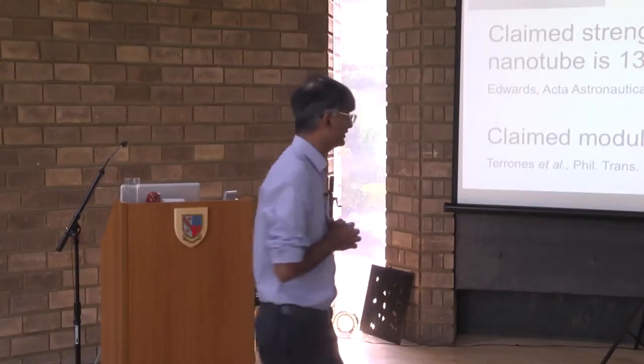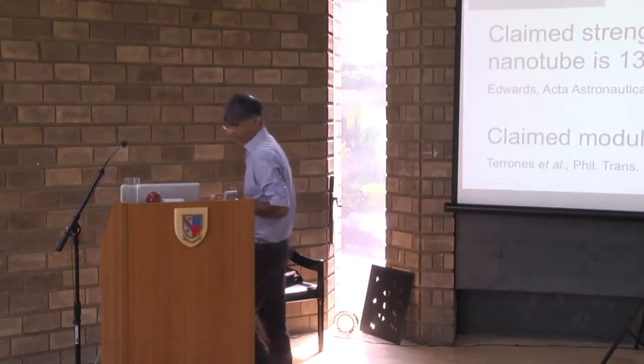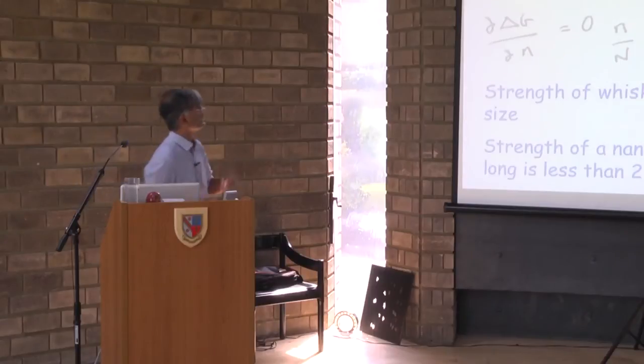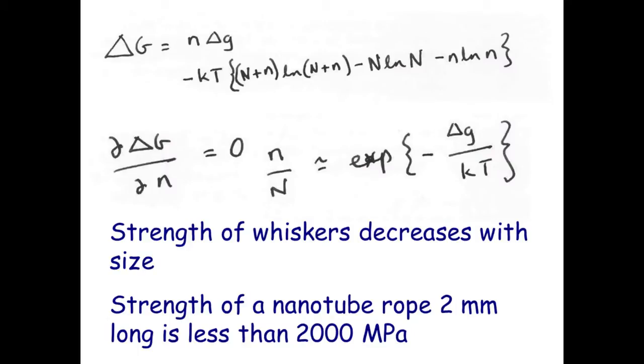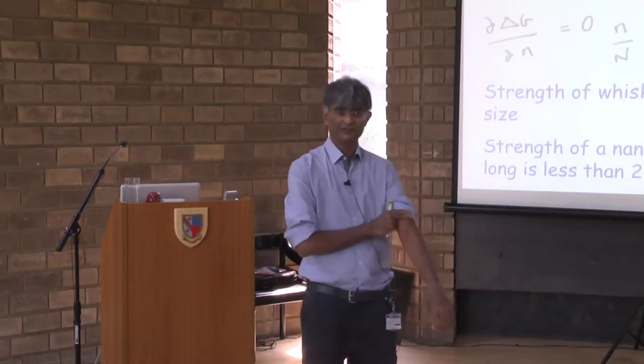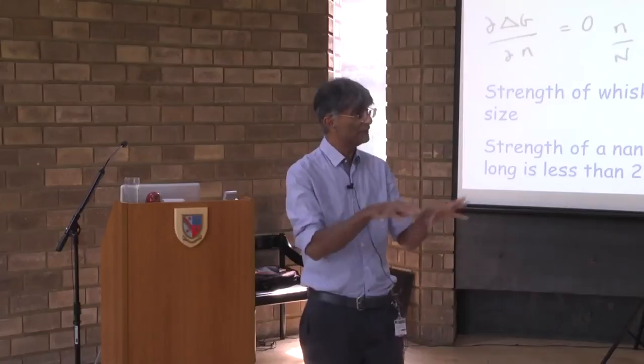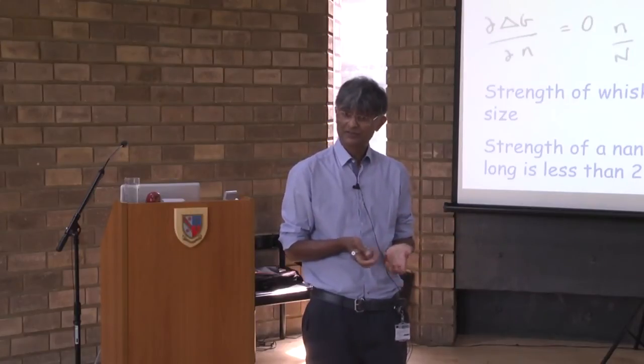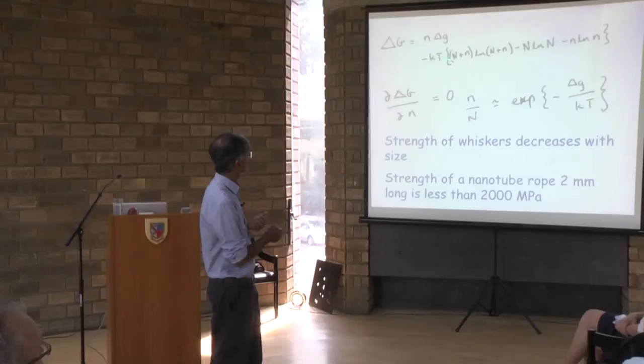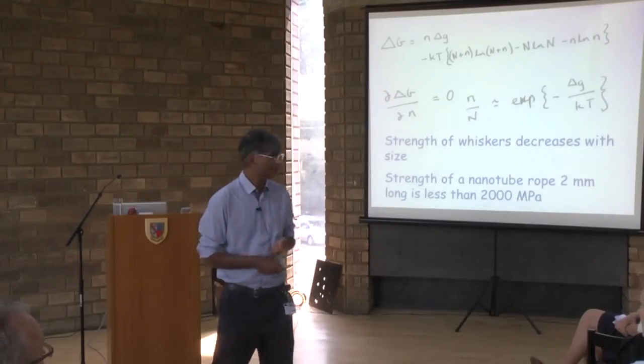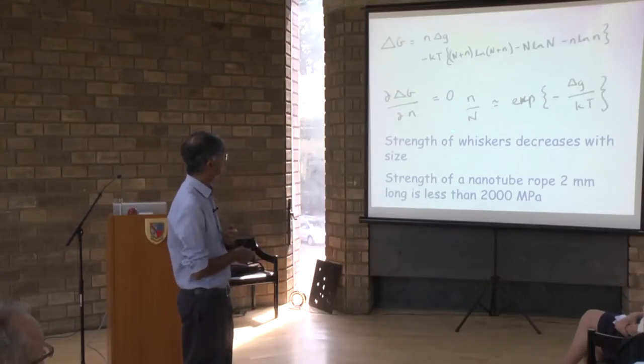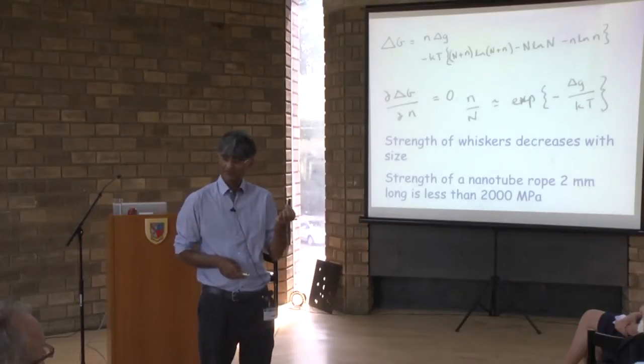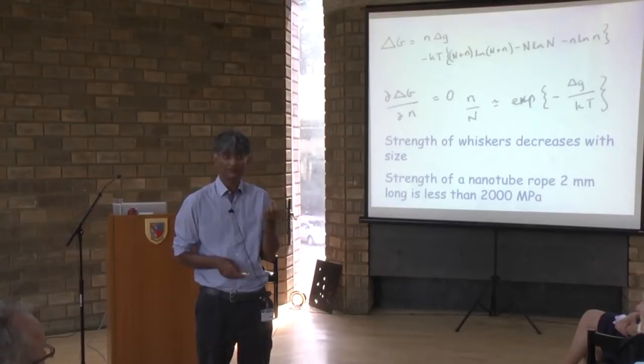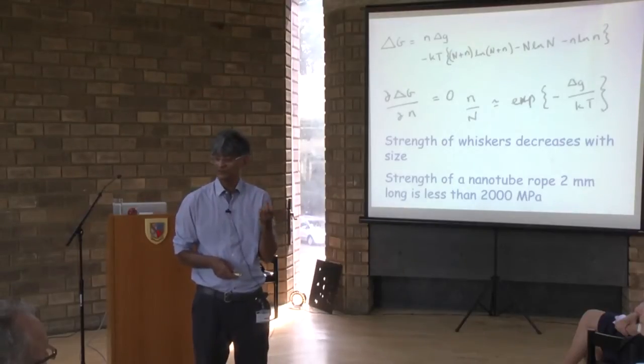As soon as you scale it up, elementary thermodynamics tells you that there is a cost to creating a defect, but when you introduce a defect, it also changes the number of ways in which you can arrange the atoms, and that's called configurational entropy, and that favors the formation of a defect. So if you balance these two terms, you get a concentration of defects inside anything that you make, which is equilibrium. That means there's nothing you can do to get rid of them. They will always be there.